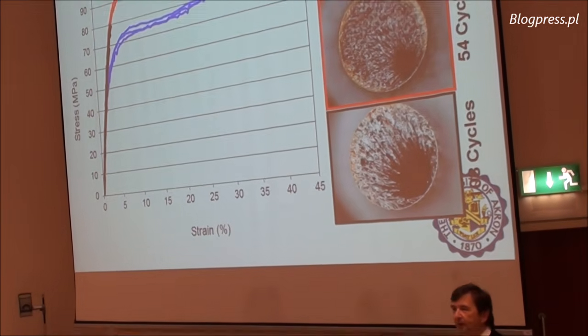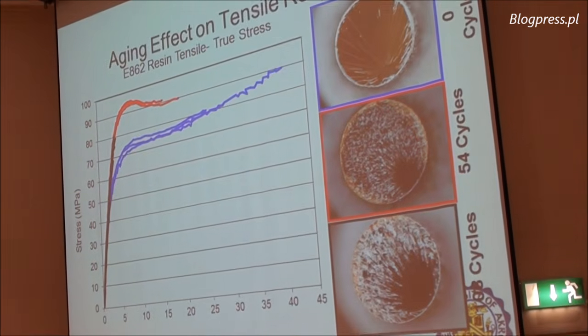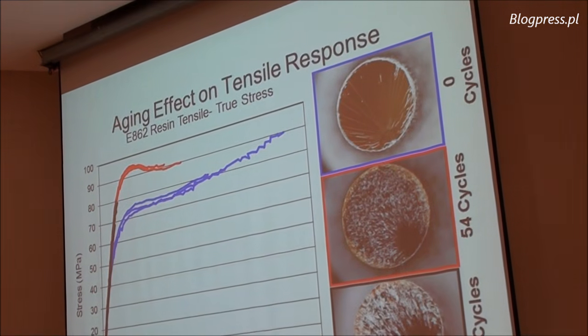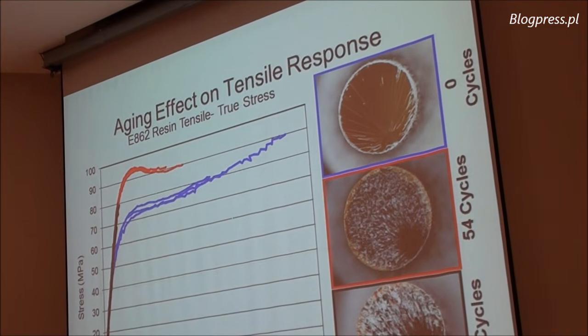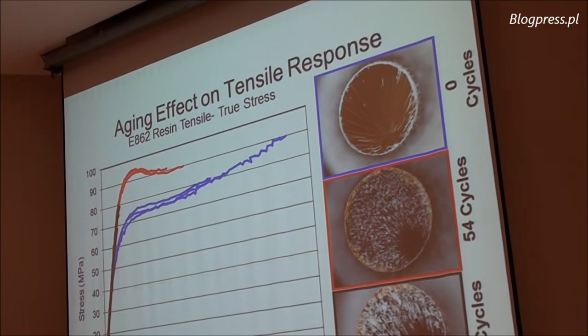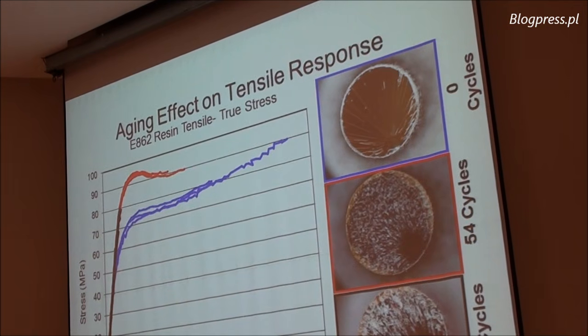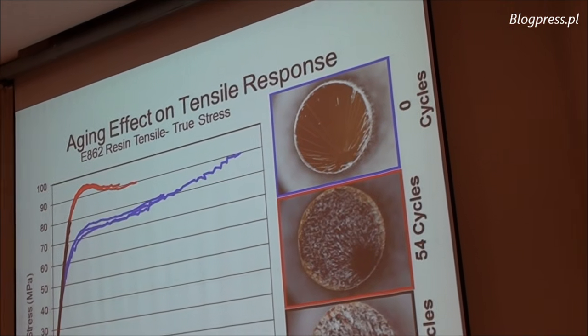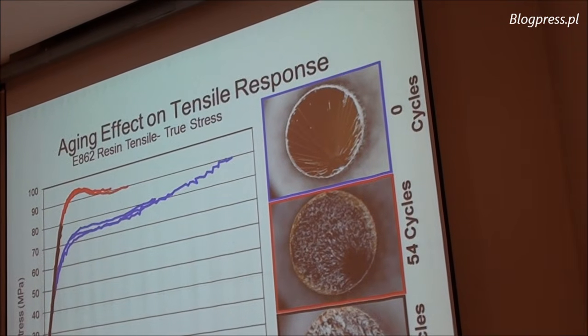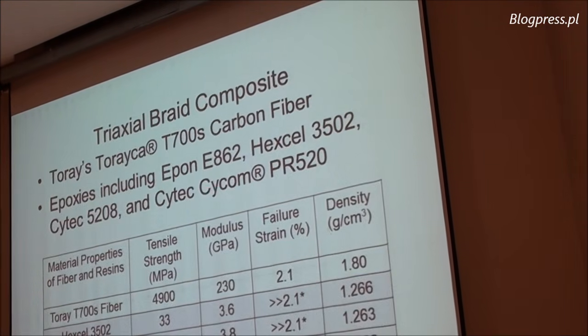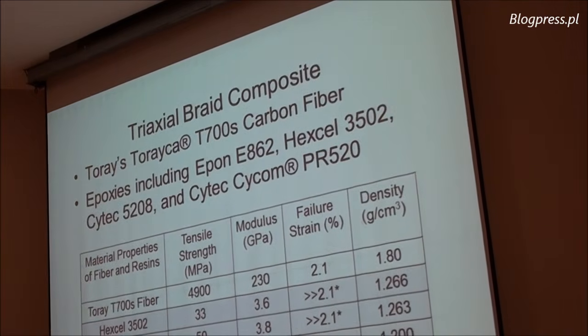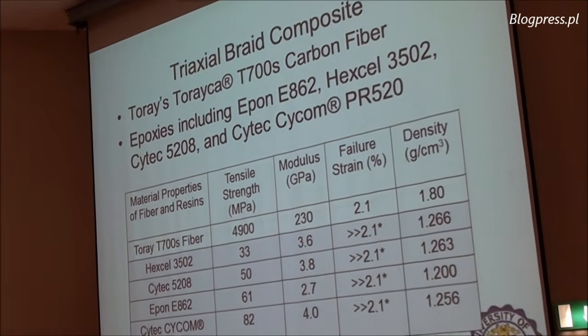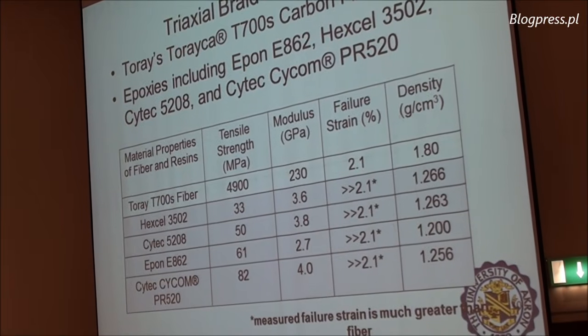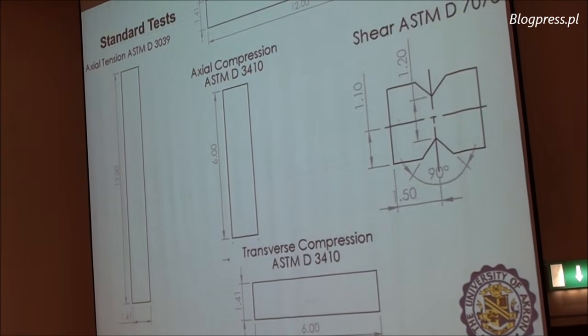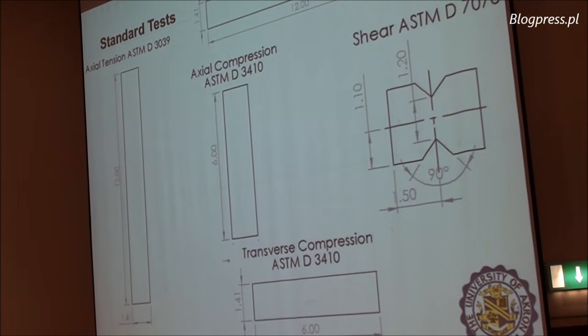So we found that indeed the aging changes the properties of the resin from very elastic plastic to less plastic and to a very brittle material. It changes also the color, as you can see through the cross-section of the broken specimen. So once you understand the limitation and behavior of the resin itself, then you can go and make a composite, and then you go and try to test the composite.